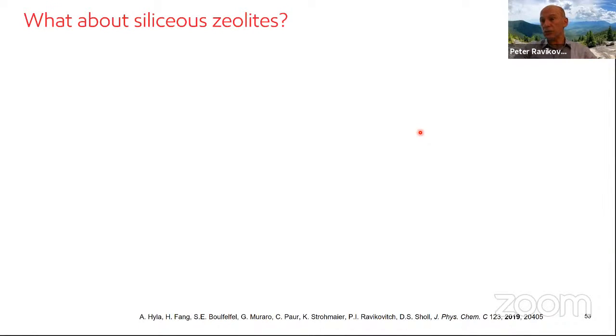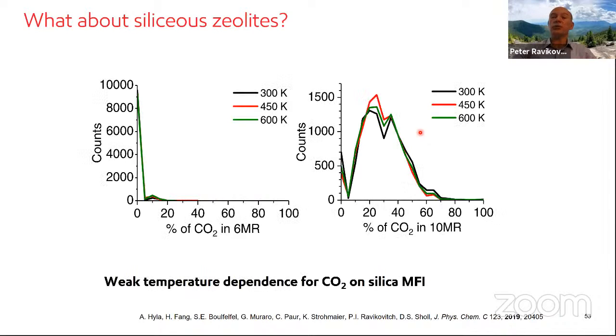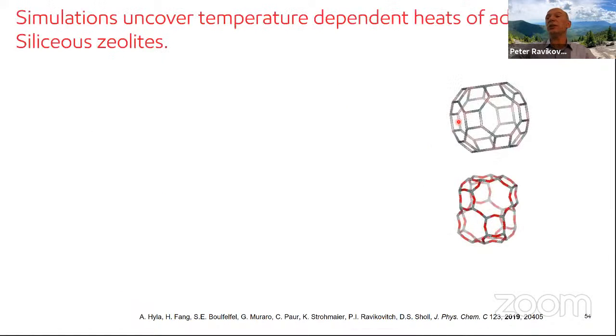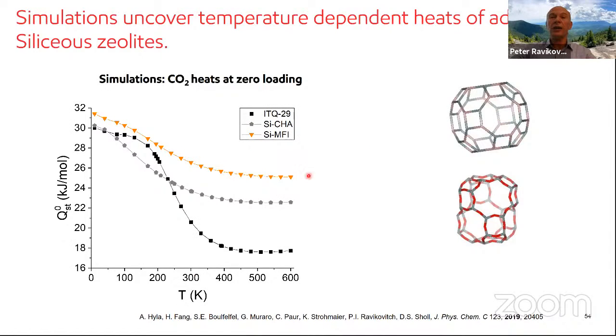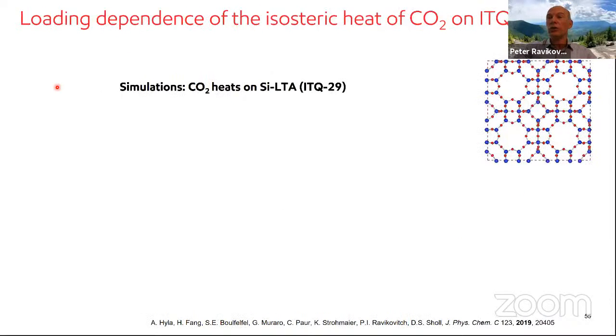So what about siliceous zeolites? We looked at typical siliceous zeolites. For example, if you look at CO2 in MFI zeolite, nothing changes with temperature. That's why the heat of adsorption is independent of temperature. However, if you look at some of the siliceous 8-membered ring zeolites, something like ITQ29, which is siliceous LTA, you start seeing a very substantial change in the heat of adsorption, especially as you decrease the temperature. And it's very dramatic, especially for ITQ29. It is from 18 kilojoules per mole to 30. That's a really huge change. So what's going on here?